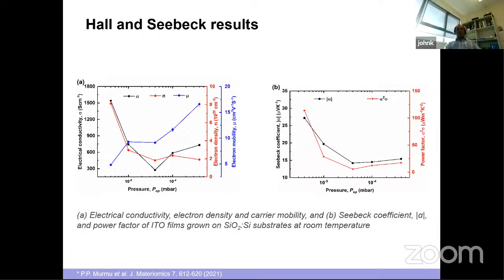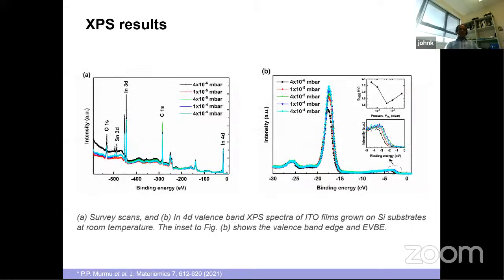Then we looked at the electrical conductivity. Again, that's what matters in terms of thermoelectrics. You can see that the thin film deposited at 4×10⁻⁶ millibar has the highest electrical conductivity and also Seebeck coefficient. Normally, as I said, the decrease in conductivity is attributed to the decrease in electron density with increasing operating pressure, because you're filling up the oxygen vacancies. Also, the presence of indium clusters provides some free electrons, which contribute to the conductivity of the ITO films. Again, the decrease in Seebeck coefficient and power factor is likely due to energy dependent scattering, which increases with operating pressure as well. So you can see a nice correlation between both the electrical conductivity and Seebeck coefficient.